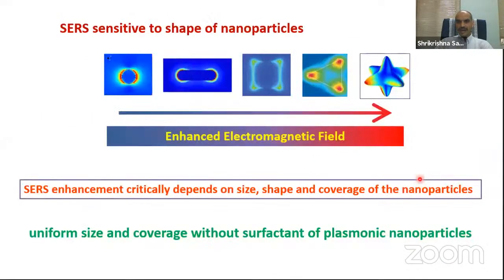So if I want to get a higher enhancement, I should first have a uniform size, because then I will know the hotspot. If this particular nanoparticle is of this size, and suppose two nanoparticles attach to each other and give me, for example, a nanorod-like shape, what will happen? Then I will have enhancement only at this region, and there will be no enhancement at this other region. So I have to have, for example, spherical nanoparticles. They should be separated from each other, they should be of the same size, and there should not be any capping agent. Then I will get maximum enhancement.